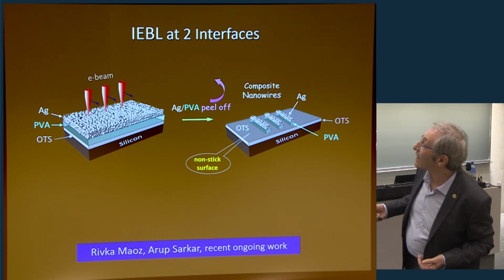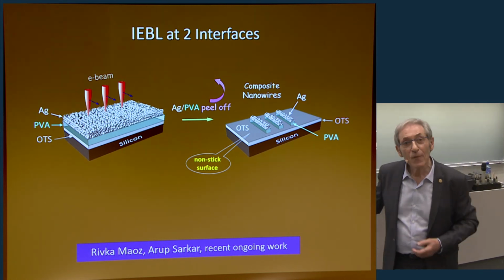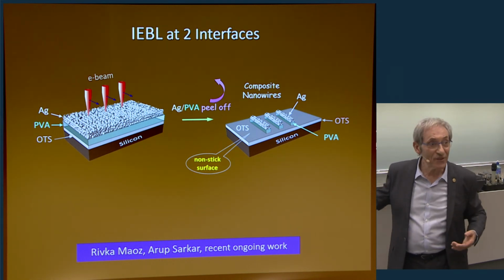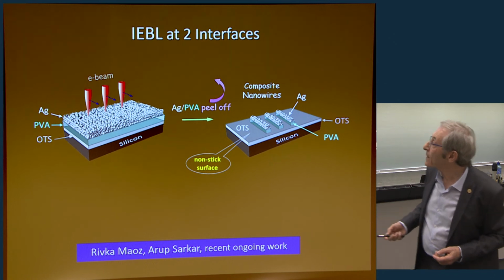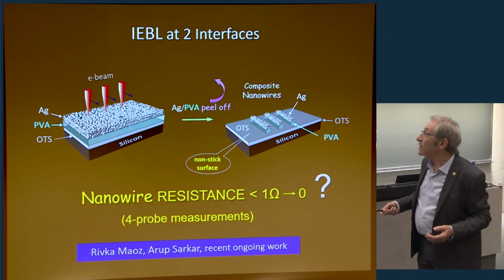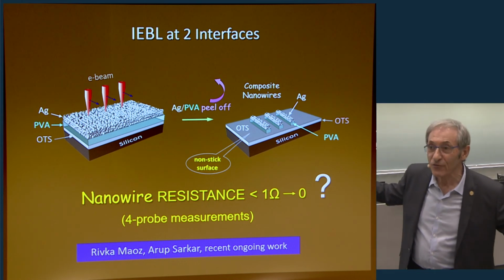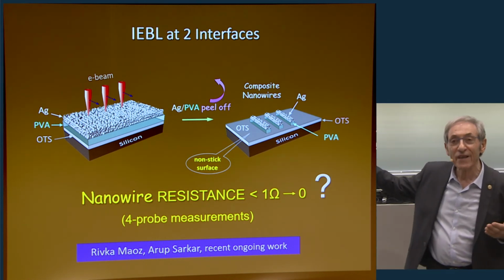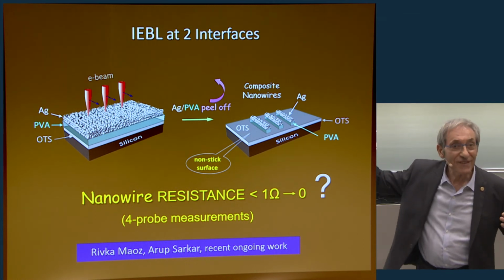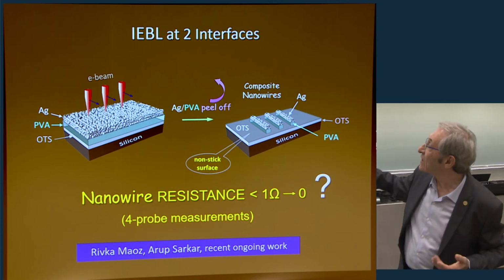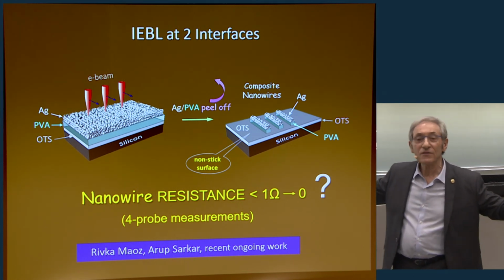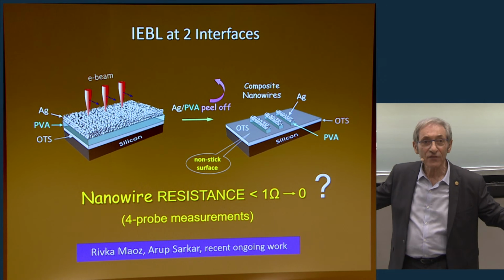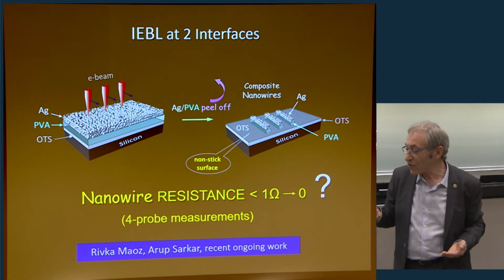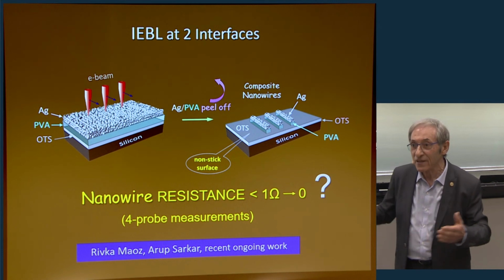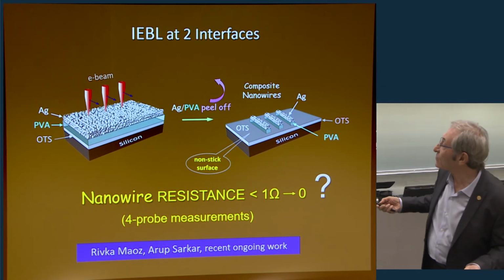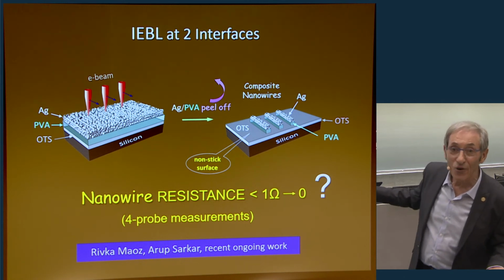So what is the finding here? These are much, much better conductors with the PVA, silver on the PVA. If we use the same measurement with 2 probes as before, now we are down. What I've shown before are kiloohms on the scale and hundreds of ohms. Here, on lengths of hundreds of micrometers, we may have 20 ohms or so. But if we use so-called 4-probe measurements, in which we get rid of contact resistances, now we are down to what appears to be nothing, less than 1 ohm.